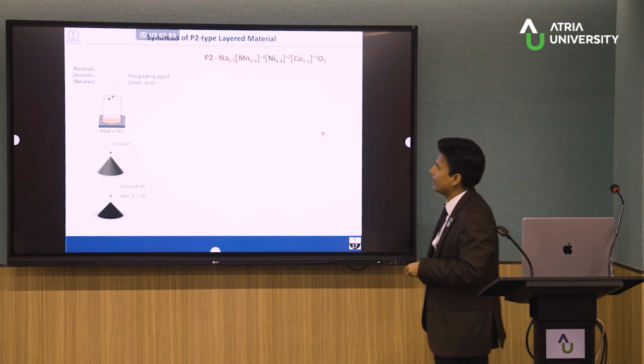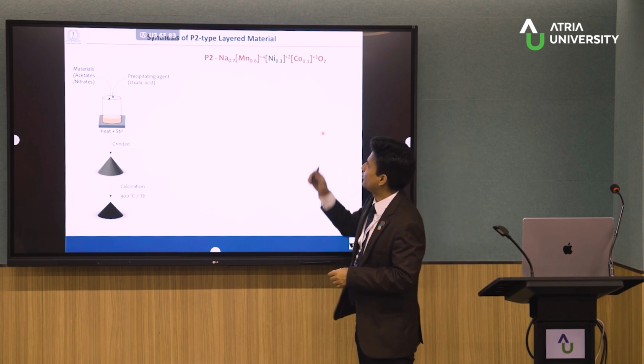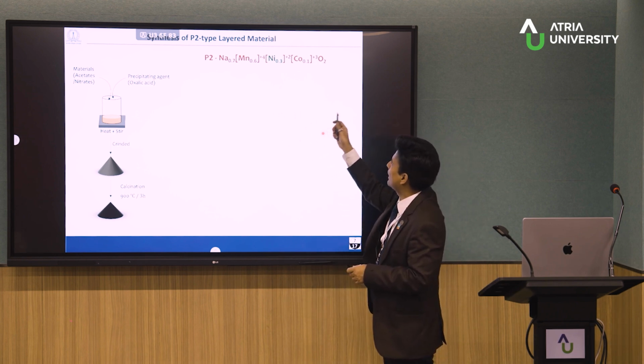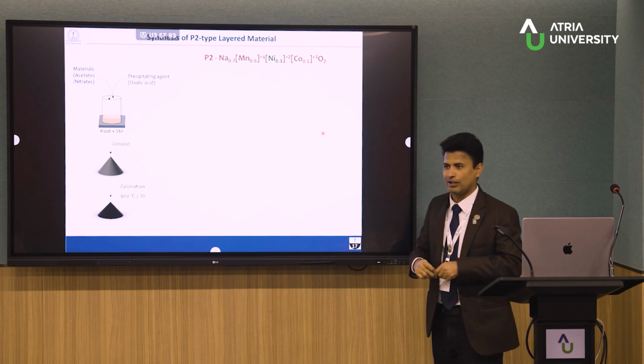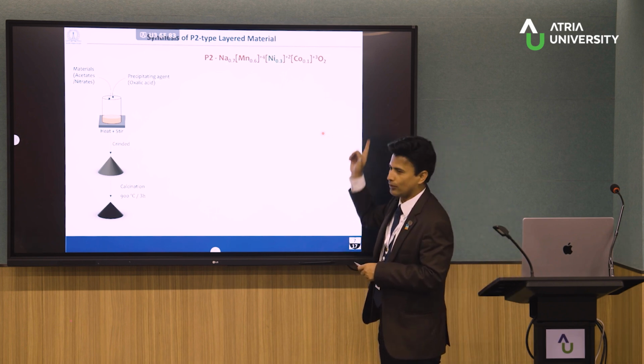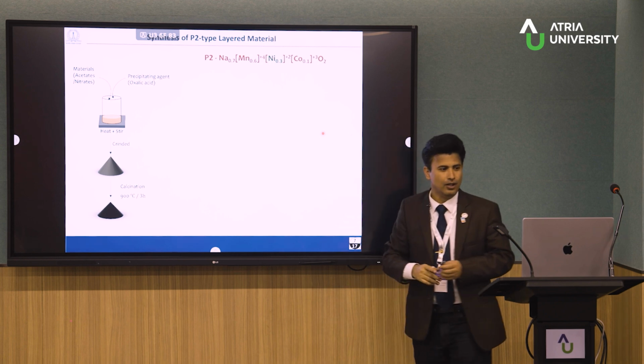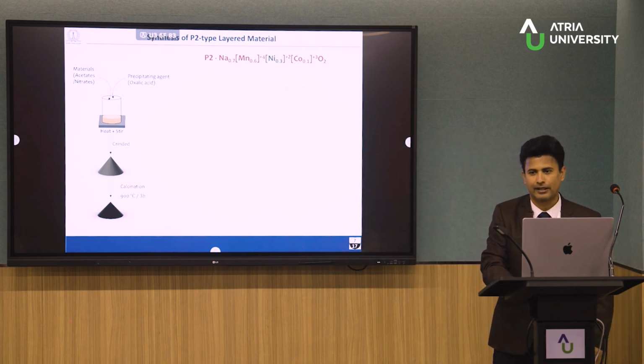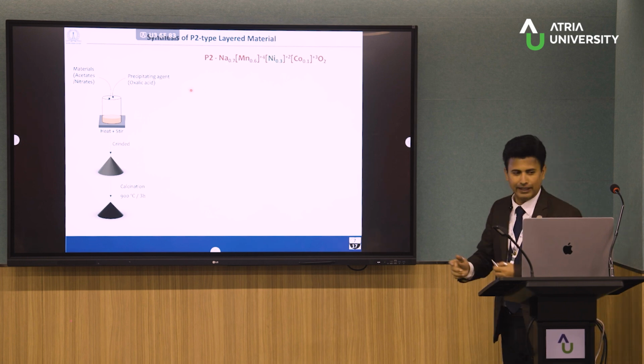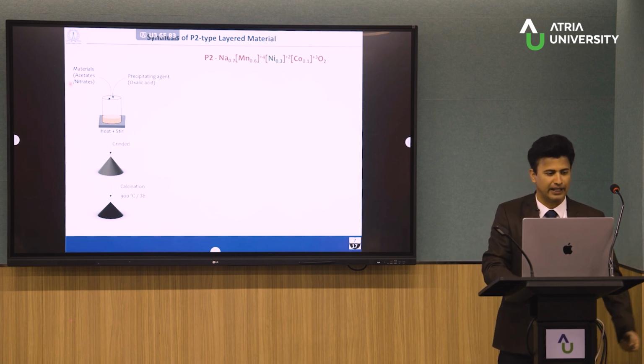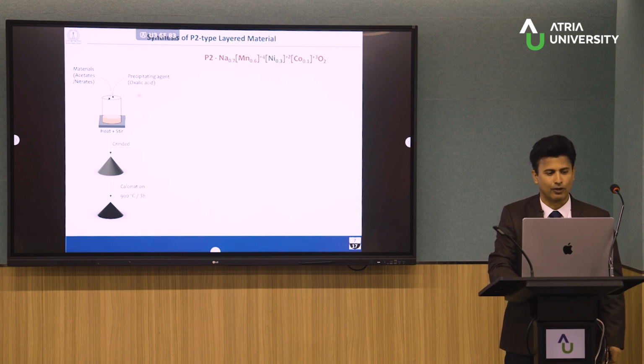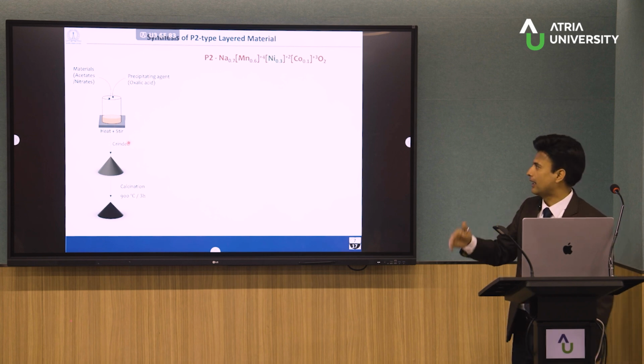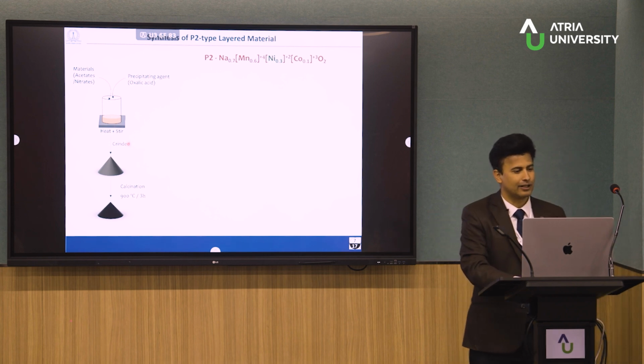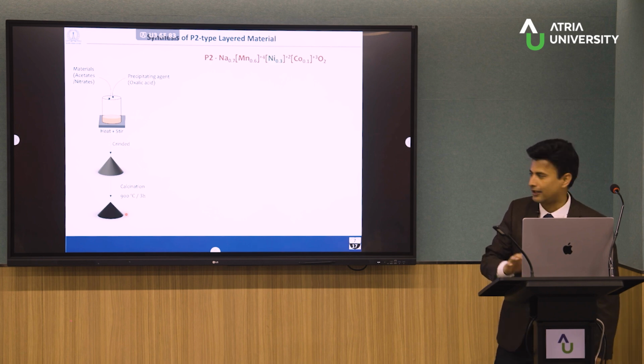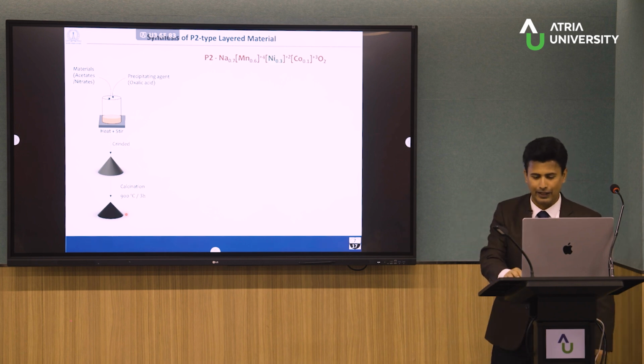So we designed one new composition called Na0.7, Mn0.6, nickel, cobalt, O2. So we all know about the system called Na0.7 MnO2. So rather than 100% manganese, we try to dope some nickel and cobalt to get this new composition. This is made very easily: nickel acetate, manganese acetate, cobalt acetate in stoichiometric ratio we put, and we have some oxalic acid. When we heat and stir and get the excess water out, we can get some intermediate complex, and when we heat that at 900 degrees for 3 hours in air, we can get this phase pure material.